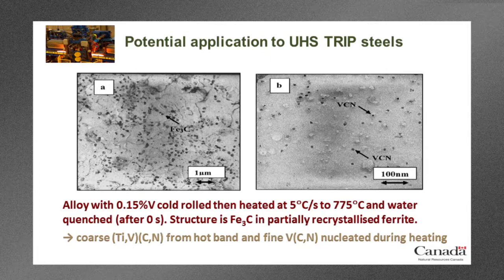This is an experiment where we took the cold strip and then heated it up and quenched it as soon as it got to the intercritical annealing temperature. So that would be 775 Celsius in this case. What you can see on the left-hand side is a rather coarse extraction replica image, and at that point what we have is a ferrite microstructure, semi-recrystallized ferrite microstructure with quite coarse cementite precipitates which haven't yet dissolved once we get to the intercritical annealing temperature at a time of 0 seconds where we quenched this sample.